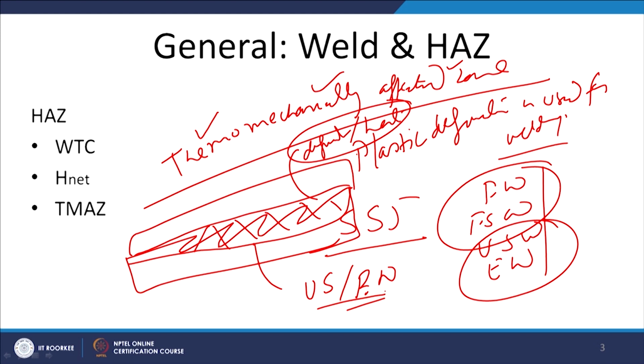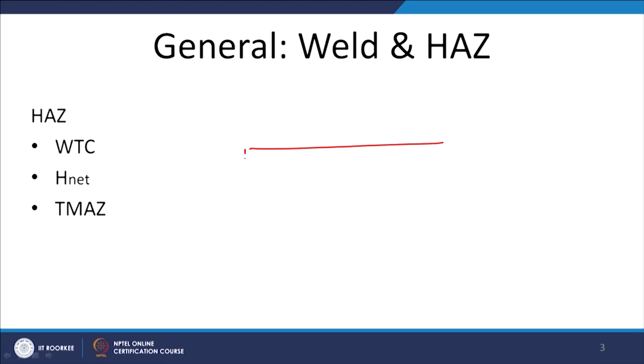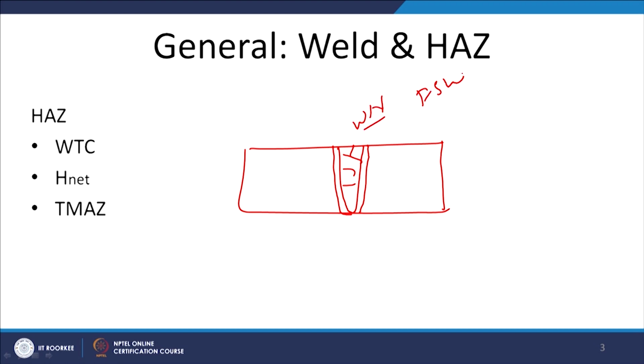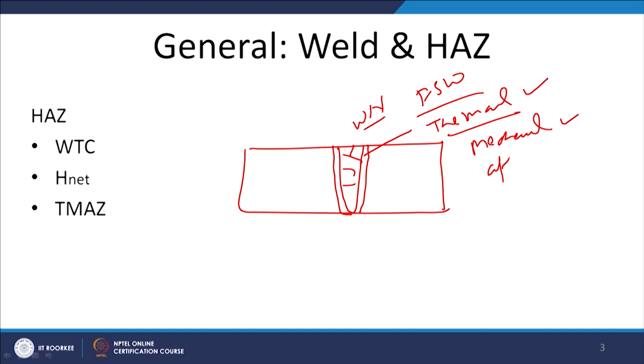But in case of friction stir welding, the complete recrystallization of the weld nugget takes place, while next to the weld nugget we find a very small zone which has the effect of the heat as well as the deformation. So, the zone which is completely deformed, fractured, refined is called weld nugget in case of FSW, while the zone next to the weld nugget is the zone which experiences both the effect of heat and the effect of deformation. So, that is why it is called thermomechanically affected zone.